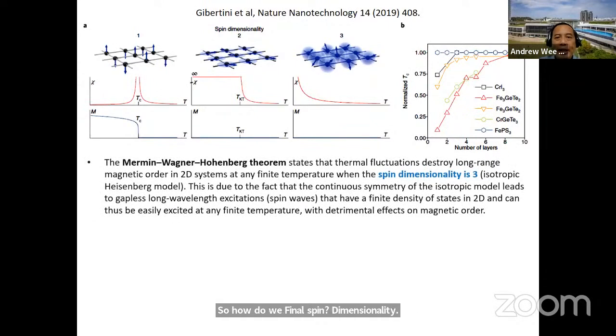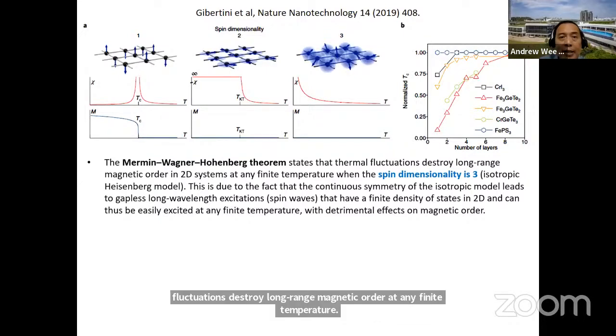The Mermin-Wagner-Hohenberg theorem states that thermal fluctuations destroy long-range magnetic order at any finite temperature when the spin dimensionality is 3. Okay, so this means that if we have an isotropic Heisenberg model like this, you have gapless long wavelength excitations being formed, they have a finite density of states, and thus they are easily excited, and this has detrimental effects on magnetic order. So it's not possible for such isotropic materials to be magnetic.